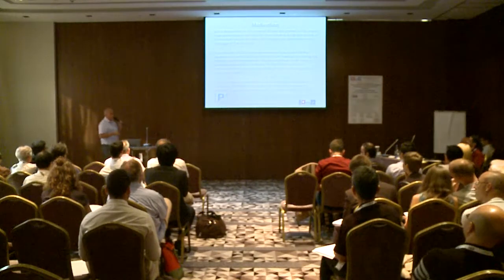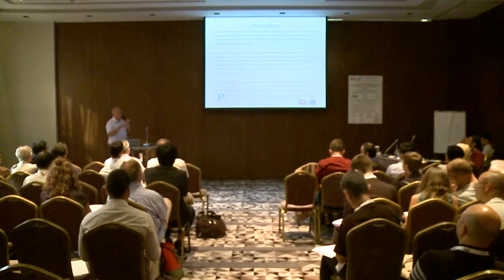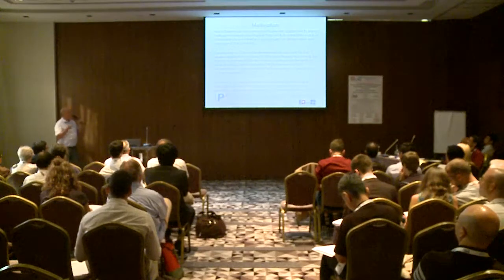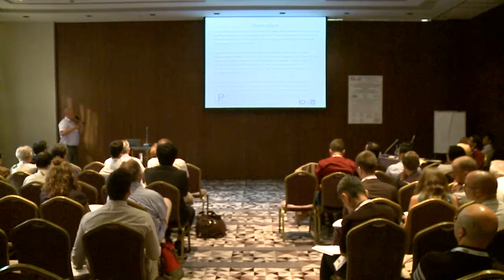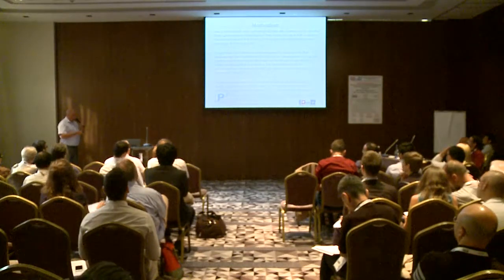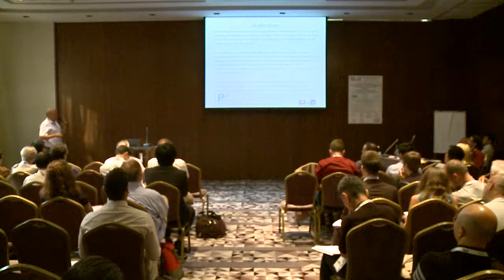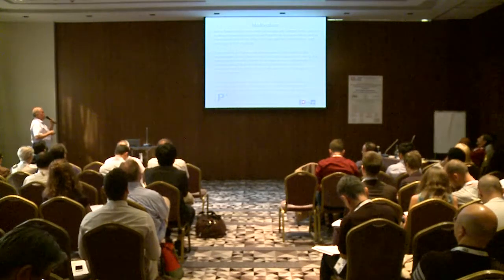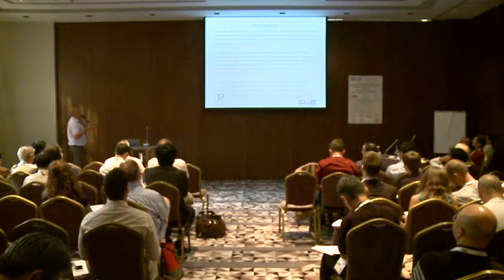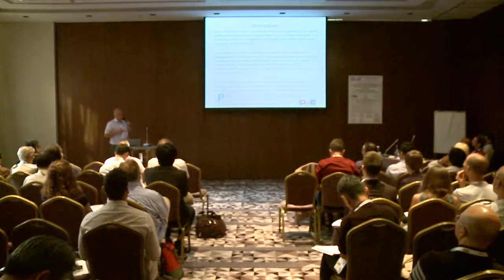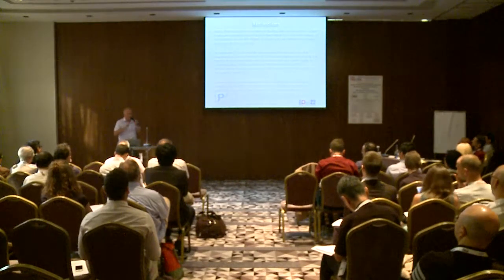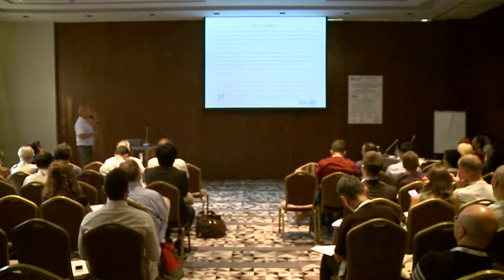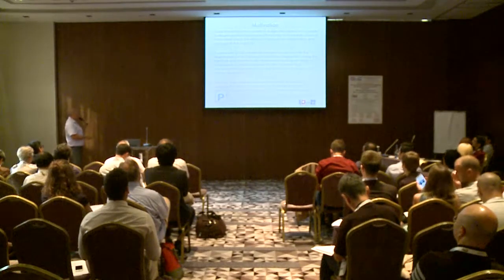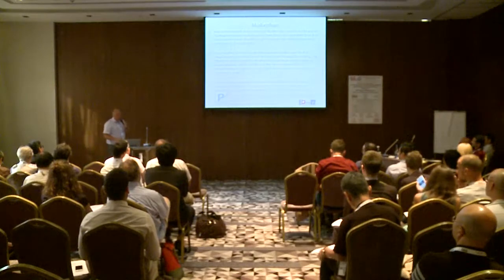For similar reasons as exposed this morning by Antonio Alvaro, in order to get further insights about the effects of hydrogen on crack tip plasticity, we decided to consider a simple material, mainly a ferritic microstructure, and for that we selected a commercially pure iron.